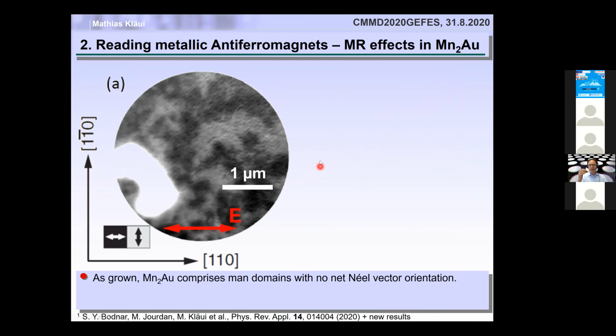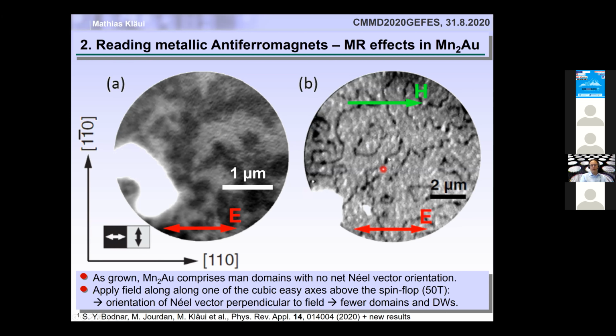So if you have a conducting antiferromagnet, firstly, you can then do imaging. That's XMLD PEM of manganese gold, which as grown has similar amounts of white and black domains, meaning the Néel vector being right, left, or up, down. And as I'll explain when I come to the writing part, if you then make all the Néel vectors point up, down, then you get this configuration where there's still some domain walls or domains where there is some Néel vector pointing right, left, but mostly it's light gray, showing that the Néel vector is up, down. So again, we can do imaging, but that is not practical for applications.